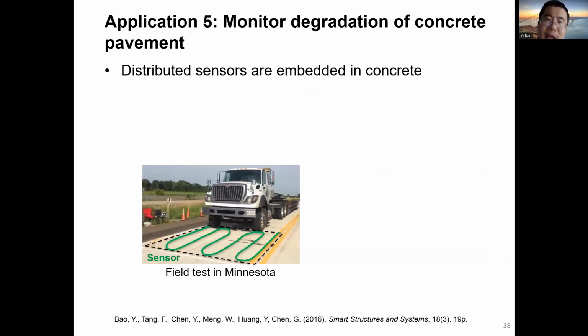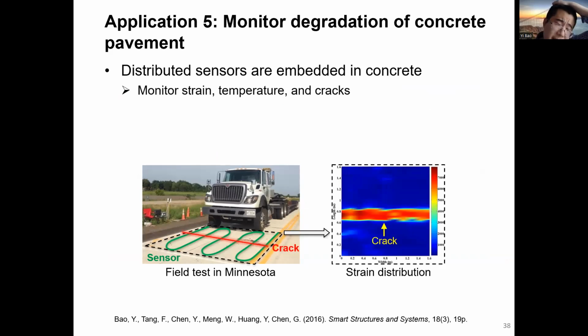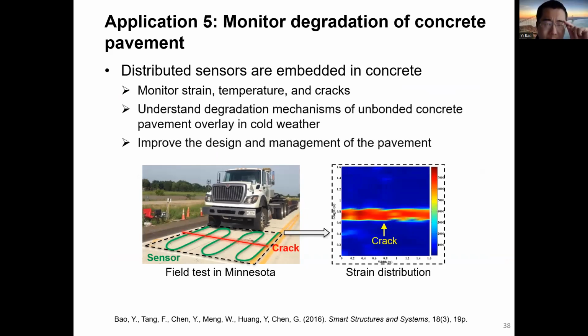Those applications mainly focus on laboratory testing. So how about the field testing? We have collaborated with Minnesota DOT and applied distributed sensors to some field projects such as the pavement overlay project. In this project, we used the fiber optic sensor. We embedded the fiber optic sensor during concrete casting, and then we used the sensor to monitor the temperature change, strain change, and we also applied the truck load to generate the cracks. And the sensor captured the cracks successfully. And the sensor data have been used to improve the design of concrete and the unbonded pavement overlay.